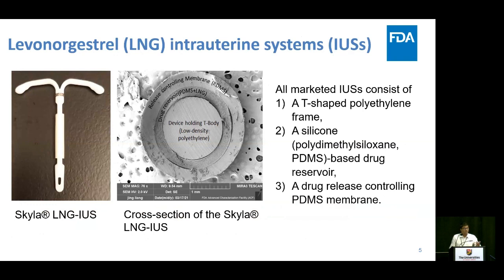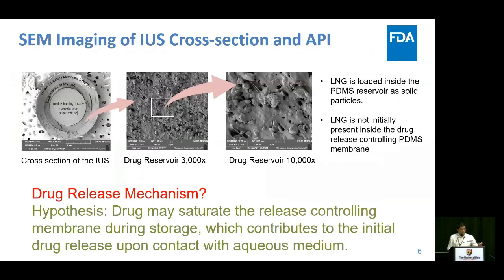All these intrauterine systems usually have three parts: a T-shaped polyethylene frame, a silicone-based drug reservoir, the inner ring here in the cross-section, and also a PDMS membrane that eventually controls the drug release. Now, if we look closely in this SEM image, this is part of the drug reservoir. Here you can see the presence of solid drug particles. We also examined the membrane itself, but we couldn't find any solid drug particles in the membrane.